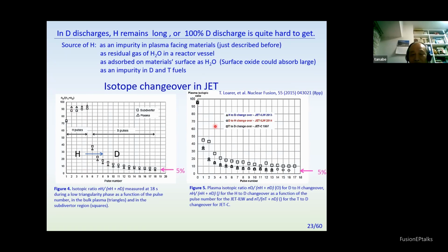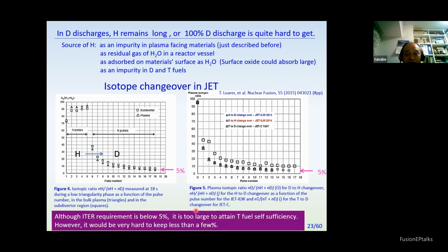This case is from hydrogen-deuterium discharge to hydrogen discharge, and again 5% of deuterium remains for a long time. This 5% is okay for ITER, because ITER requires 5%, and from the burning point of view this is okay. But from the tritium fairing and self-sufficiency point of view, it is too large. So it should be programmed, and also the existence of low hydrogen, normal hydrogen, also gives disturbance to this.